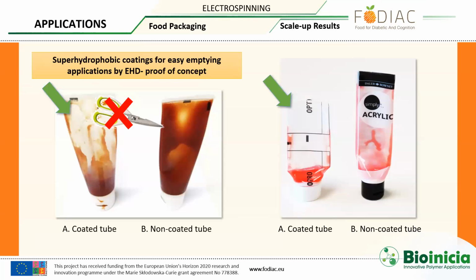And as you can see here, with a non-coated tube, there was always way more material left on the walls than in the coated one. We did this by weight differences, and there were significant differences, not just visually but also quantitatively. We have not shown it here, but we also did some migration studies, which indicated that there was no migration of the coating, especially of the particles, onto this material. So that was very successful as well.